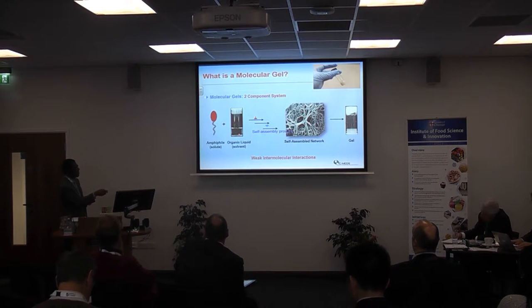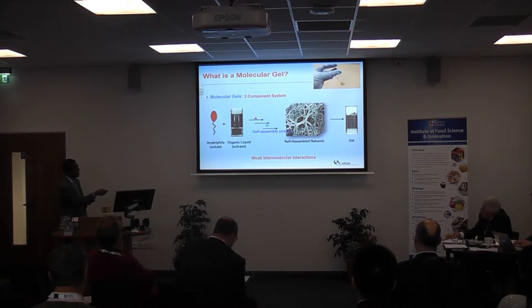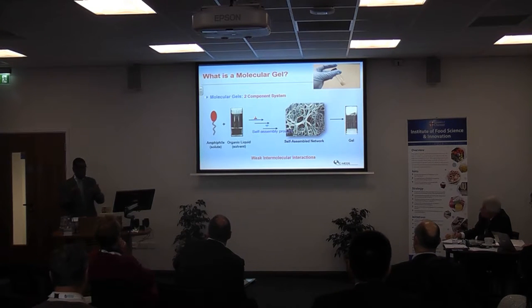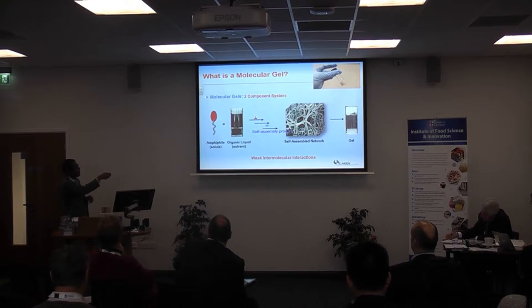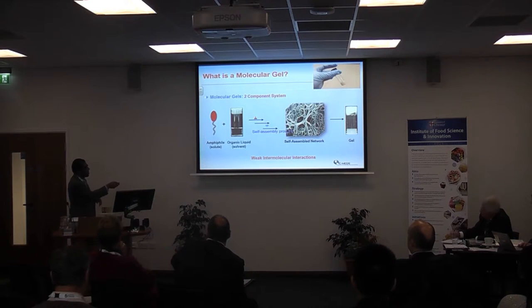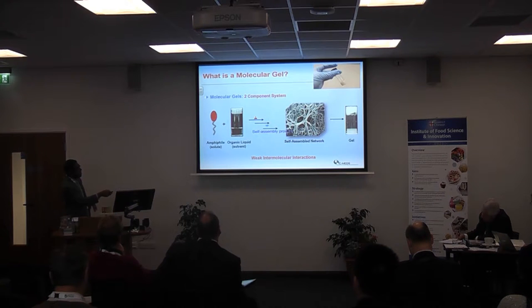If you mix with the solvent, in this case it is water or it can be organic solvent, how do they assemble? Because these molecules will talk to each other. The head group, the hydrophilic part, will interact with the hydrophilic through hydrogen bonding or some other interactions, and the tail will interact through hydrophobic interactions. They make bilayer membranes. And these bilayer membranes are growing in one direction, making a beautiful fiber. Millions of fibers are forming together, assembling together, and they create this kind of three-dimensional network. Initially it was a liquid, it was flowing, right now it is not flowing.